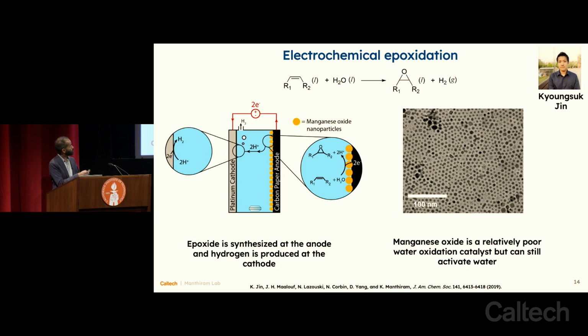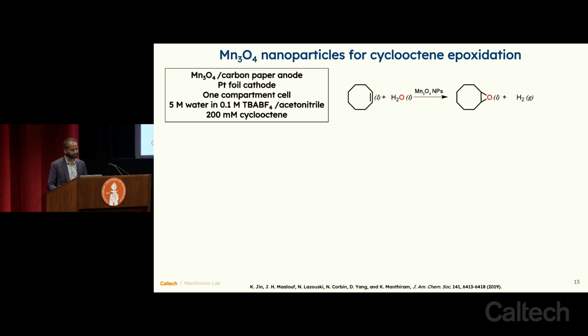That was really our goal. And so in this reaction, what we'd want to do is activate water at the anode, take that O atom, place it on the olefin, and then take the electrons, send them through the external circuit, take the protons, send them through the electrolyte, and make hydrogen on the other side. And we reasoned in our early work that manganese oxide could be a good catalyst for this, that it's known to activate water, but isn't so good at recombining those oxygen atoms, and that may give us just enough time to have this olefin sweep in, pick up the O atom, and make the epoxide as the product.